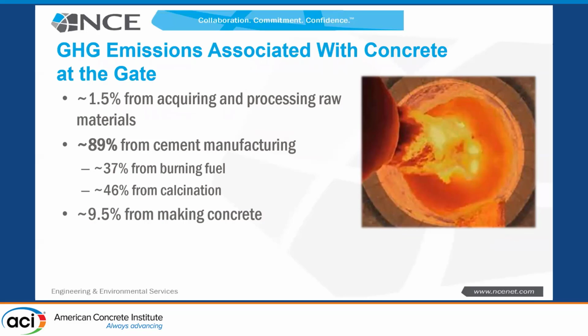Where's it coming from? If I look at concrete in a ready-mix truck at the gate, all right, it's leaving the ready-mix facility. 1.5% of the CO2 in that 10 cubic yards of concrete is basically from acquiring and processing the raw materials to make that concrete. 89% is from making the Portland cement. 9.5% is wrapped up in actually making the concrete, the aggregates and whatnot. Out of that 89% from the manufacturing, 37% of all the CO2 involved in that concrete in that truck is from the fuel burning in that kiln right there.